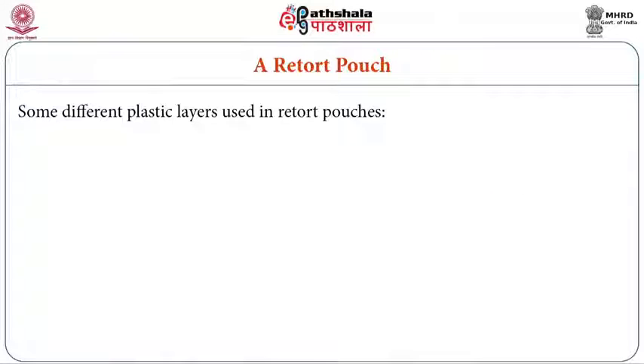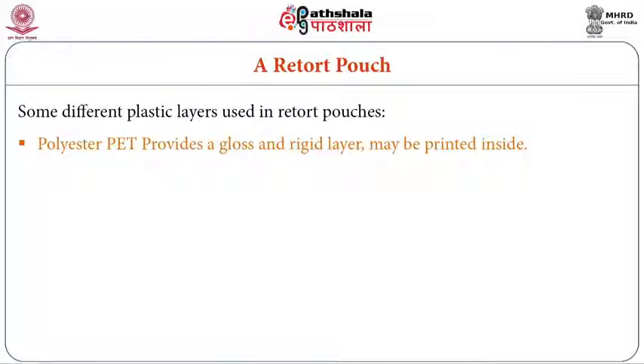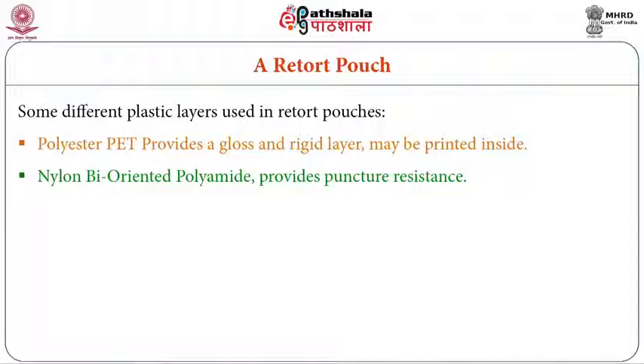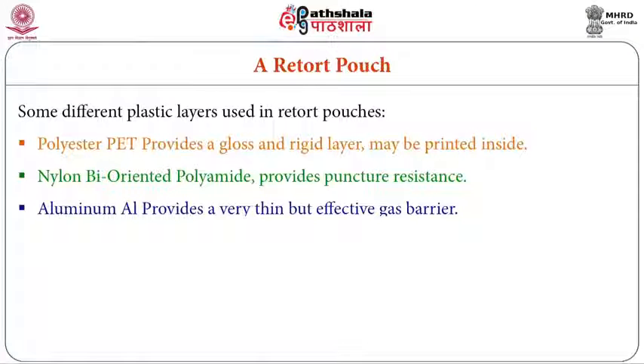In retort pouch processing, there may be different types of packing materials laminated into a pouch. Those packing materials provide different physical properties and different barrier properties against oil, water and other gases. In the slide you can see polyester PET, polyethylene terephthalate, provides a glossy and rigid layer that may be printed inside. Next, nylon, a bi-oriented polyamide, provides puncture resistance. If you pierce a pin into that, it offers resistance against the puncture. Then aluminum gives a very thin but effective gas barrier against the exchange of gases from the atmosphere to the food or food to the atmosphere.